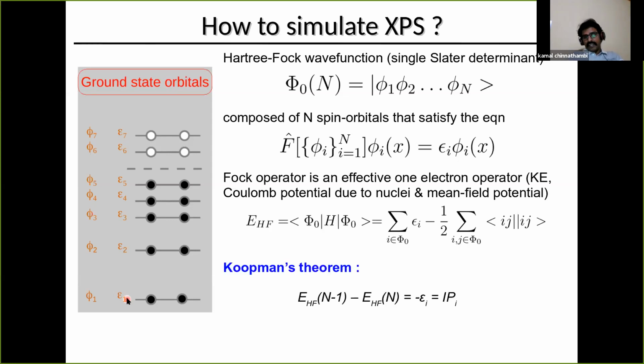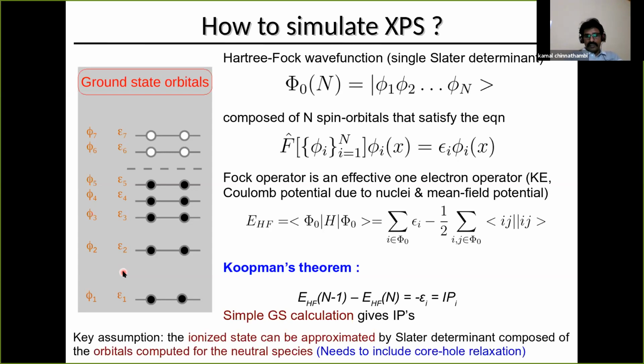Once you have this from the Hartree-Fock calculations, using Koopmans' theorem, it says that all these eigenvalues of the single-particle orbitals correspond to the ionization potential. That means the energy required to remove an electron from a particular orbital is equal to that eigenvalue. So if you want to calculate the XPS, what we need is the binding energy of an electron from a particular level, so we can use this. But the major problem is that we are doing a simple ground state calculation where there is no core hole present in our system. As I mentioned in the previous slide, we need to incorporate the core holes in order to give the correct description. That is a major approximation involved in this.